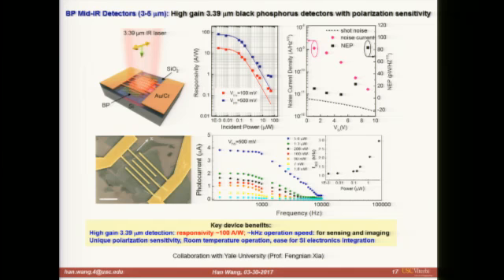The detector is not very fast. It works in the kilohertz range — this kind of responsivity is maintained up to about kilohertz frequency, so it's definitely not fast enough if you want to use these detectors for free space communication. But for imaging and sensing applications like night vision, it's more than enough, since the human eye, for example, can only respond to about 60 hertz per frame rate, per second.